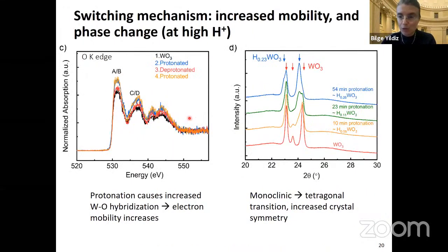We have evidence to also mobility increase, and one of that is through looking at the oxygen K-edge X-ray absorption spectra. And without going into details, what we see here is that some of these features, especially the first feature, is a measure of tungsten oxygen hybridization. And after protonation, we see an increased hybridization, and the states of that hybridization being in the conduction band means that you also have increased electron mobility.